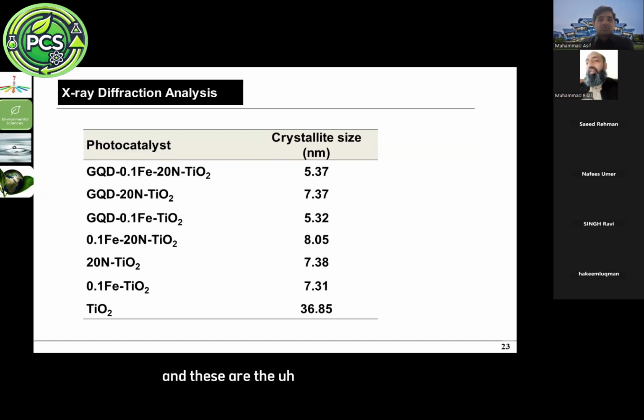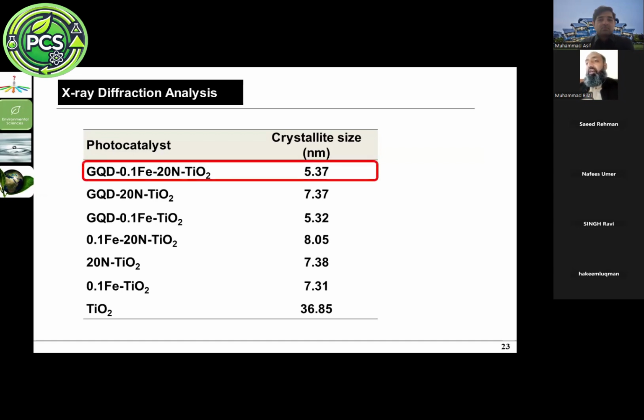And these are the characterization results of the crystallite size. We obtained the smallest size for the final graphene quantum dot iron nitrogen titania, 5.37 nanometers, as compared to the crystallite size of the titania, which was 36.85 nanometers.